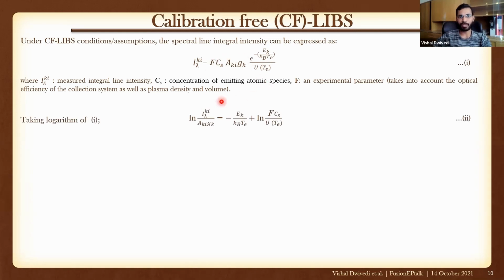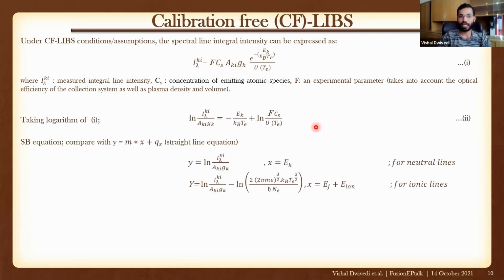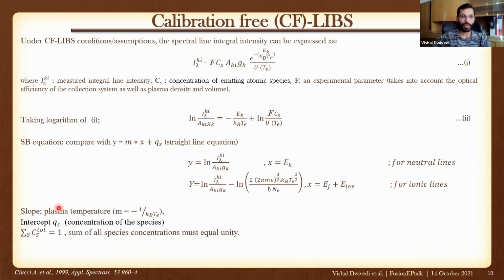Taking log of this formula, we get this, and we can easily compare this equation with the straight line equation, which is the Saha-Boltzmann equation, y is equal to mx plus intercept. And from this, we can calculate the intercept and the slope of the Boltzmann plot, and we can calculate the concentration for the neutral and ionic lines both. So plasma temperature is calculated from the slope, and from the intercept, we can get the concentration.